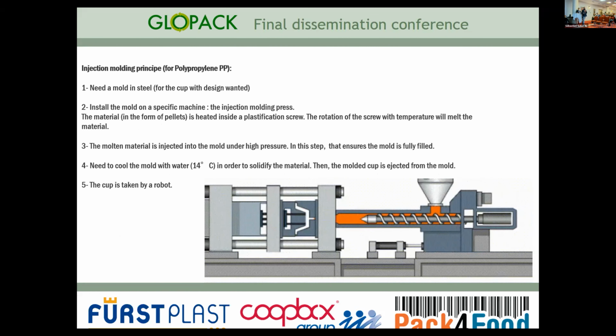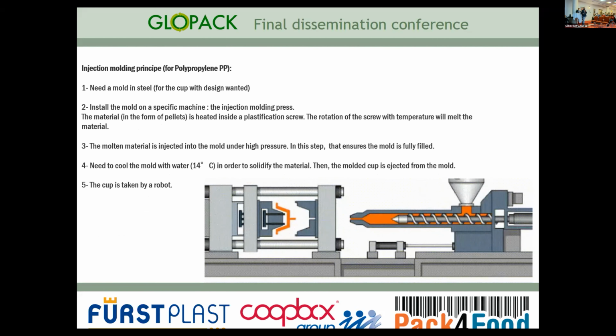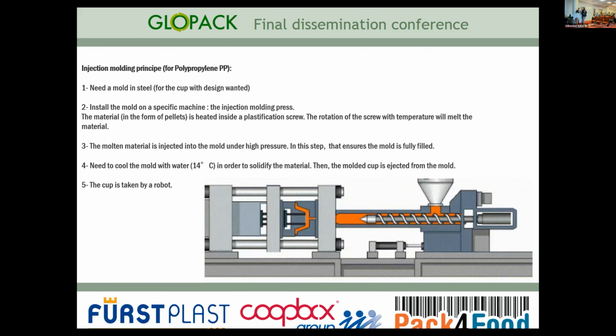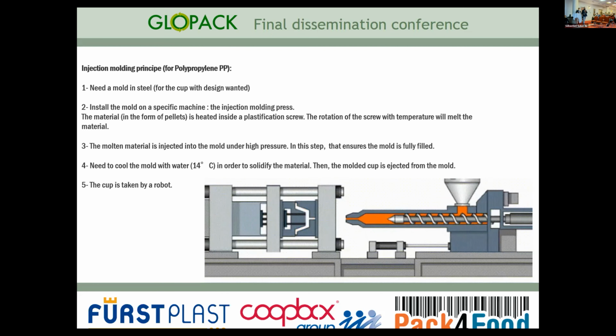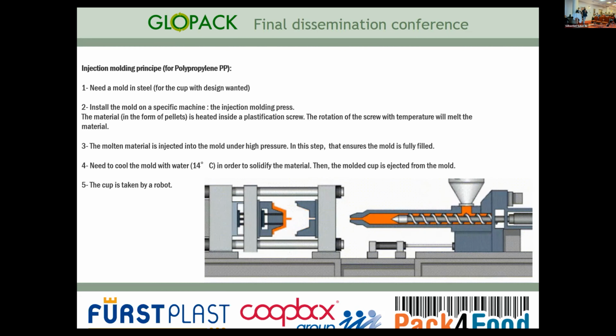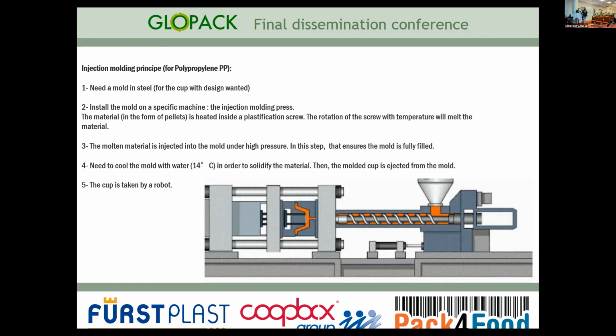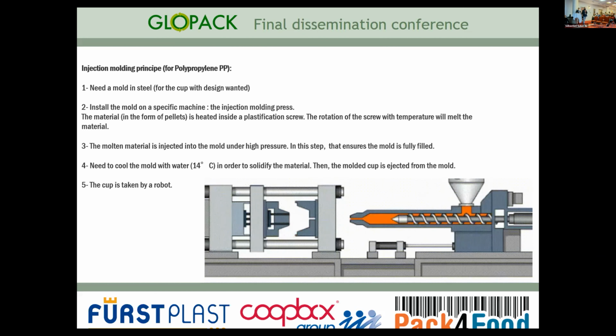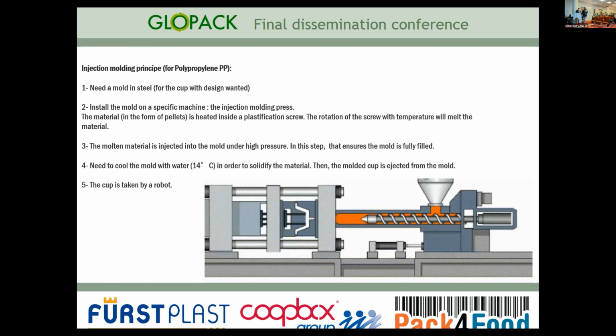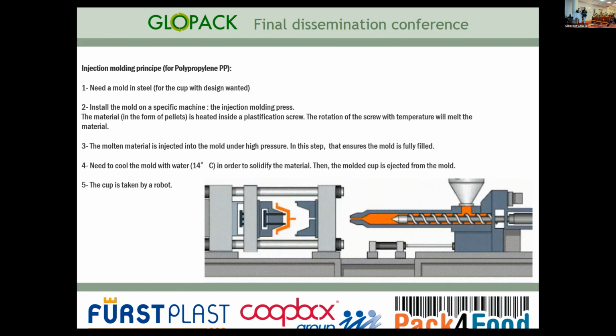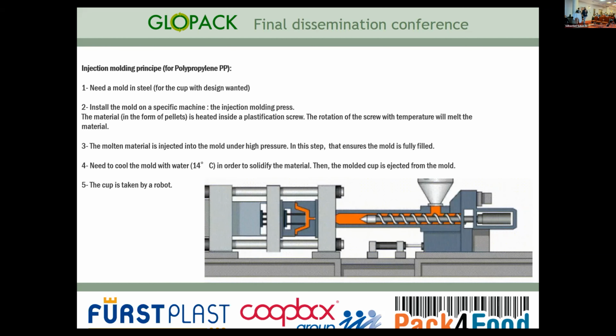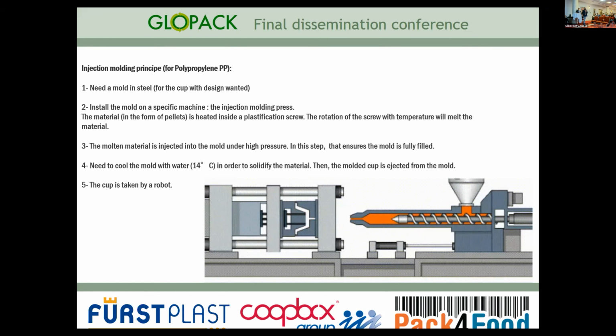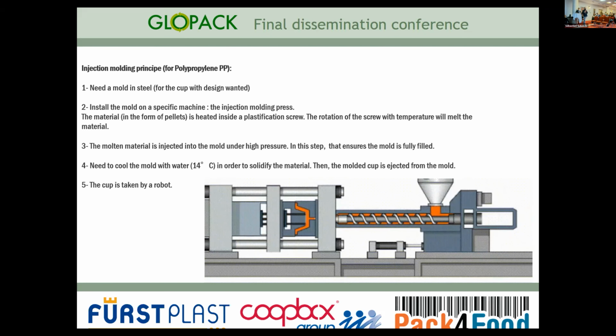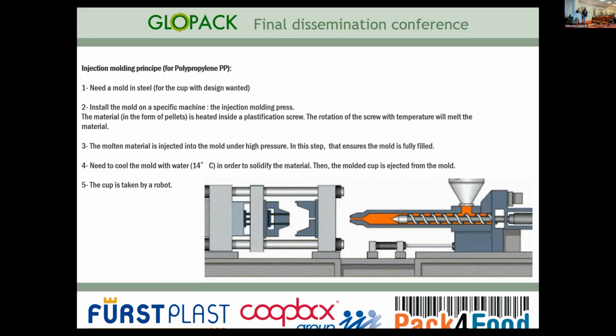We need a mold in steel for the cup with the wanted design. We install the mold on a specific machine, the injection molding press. The material, in the form of pellets, is heated inside the plastification screw. The rotation of the screw with temperature will melt the material. Then the molten material is injected inside the mold under high pressure. This step ensures the mold is fully filled. We need to cool the mold with water at around 14 degrees for polypropylene in order to solidify the material. Then the molded cup is ejected from the mold and taken by a robot.